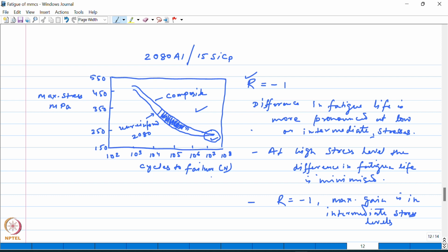Now you can also see that at the higher stress levels around this corner, here also the fatigue behavior of the composite and the unreinforced alloy is not very different. The difference between the fatigue lives is not so significant. Okay. So this can be probably attributed to the ductility of the composite material. So generally it has been found that the cyclic ductility of the composite is lower compared to the unreinforced matrix material. Okay. So this lack of ductility of the composite will actually limit the plastic strain and hence the number of cycles that can be accumulated prior to fracture.